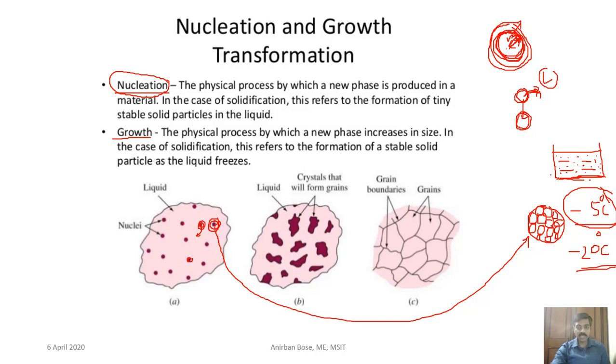But in this particular example, it is quite clear that this wall, the container, has very low temperature, so the chances are that at this position the nucleation will be at a higher rate. So the probability of forming nucleation close to the solid surface is large, right? That means all the points in the phase do not have the same probability of nucleation. So if this is the situation, then it is called non-homogeneous.